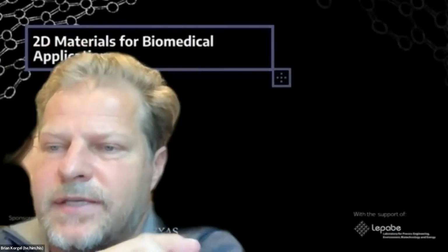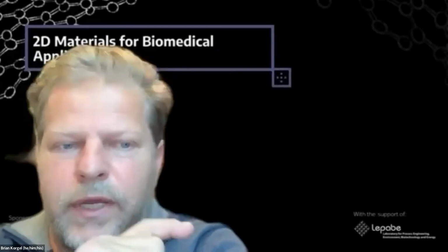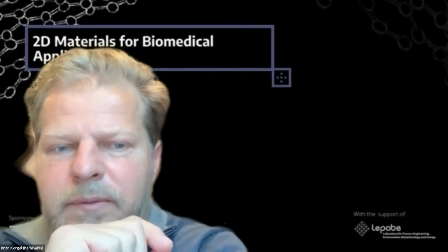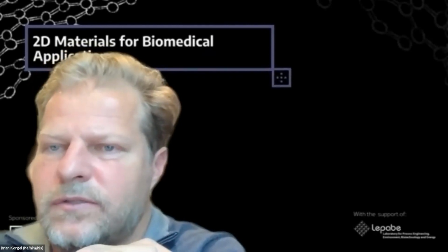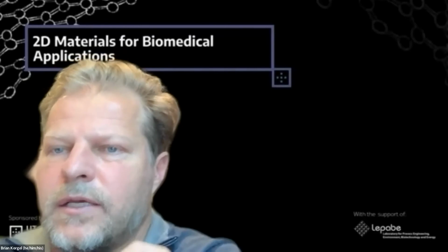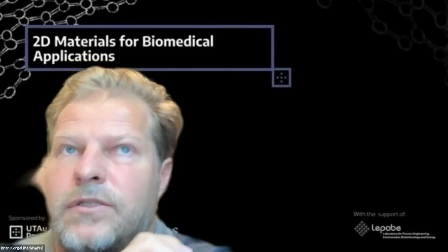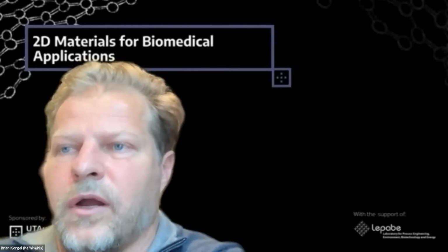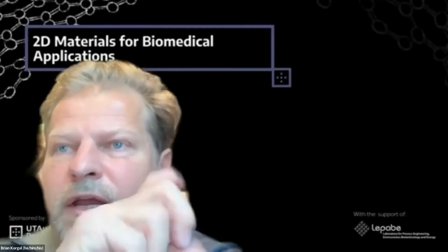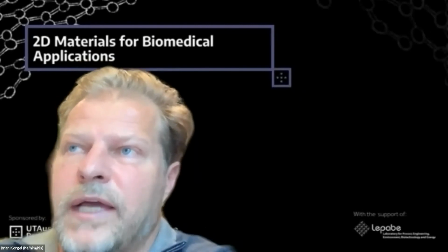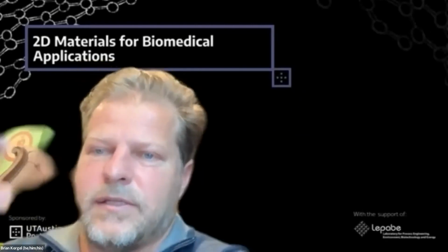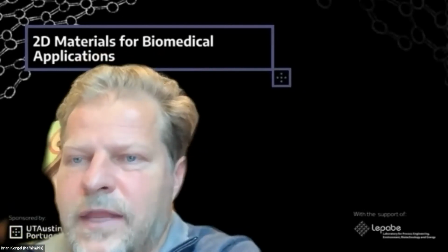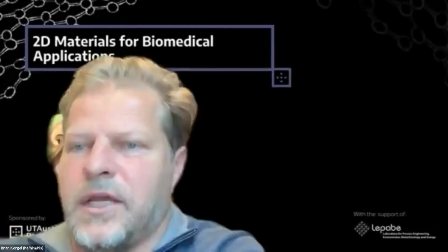Yeah. So the siloxene itself, when you react the calcium silicide with HCl, the silicon atoms are being functionalized with hydroxyls. They're being hydroxylated. So every silicon atom is terminated by either a hydrogen or a hydroxyl group, kind of alternating. And then when you exfoliate these, when you peel these layers apart, you expose all of this surface, and that's where you can get additional oxidation.